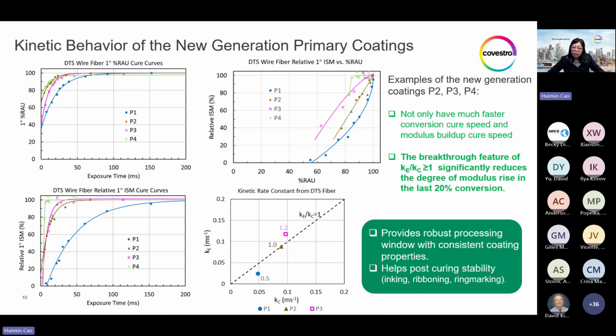And this is to support the increasing of draw speed, of course. But even more remarkable is the ISM versus conversion curve, which indeed is showing a linear shape from the P2 and decelerated increasing shape from the P3 and P4. And the new generation primary coating not only moved a lot to the right on the KC, meaning faster conversion, and so much more to the top, which means much faster modulus buildup.